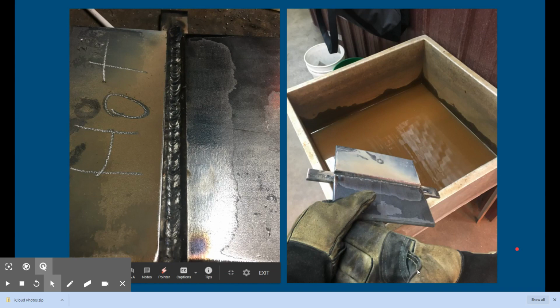So after they run their root pass, I'll do an inspection. And notice I'll have this one marked as hot, and I've got a picture of a water tank here. Now, experts will say, hey, don't quench. Never quench a bend test, because you're quenching it, you're going to harden that steel. And yes, that's kind of true. Ultimately, it's A36 steel. It's not really heat treatable. There's not enough carbon in it to really do much, even if you do quench it. But you don't want to take any chances.